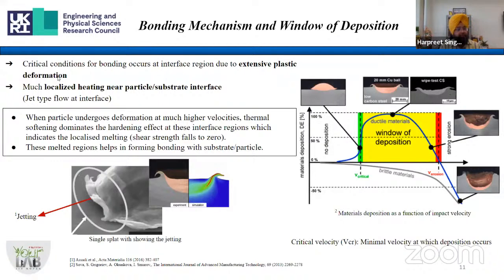One thing is that critical conditions for bonding occur at the interface region due to extensive plastic deformation. So one can expect that when the particles are coming with very high kinetic velocity, they are going to stop all of a sudden within a very small standoff distance. So you can see that there will be extensive plastic deformation, or what we call severe plastic deformation, taking place in less than a second, or in microseconds and so on.